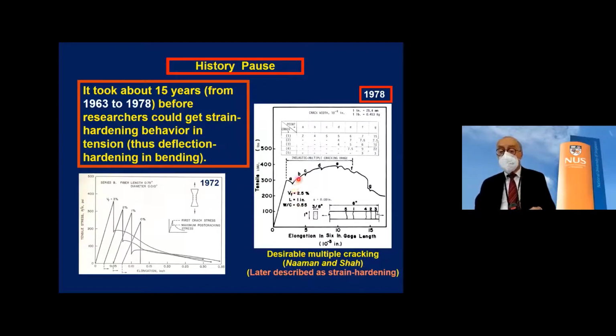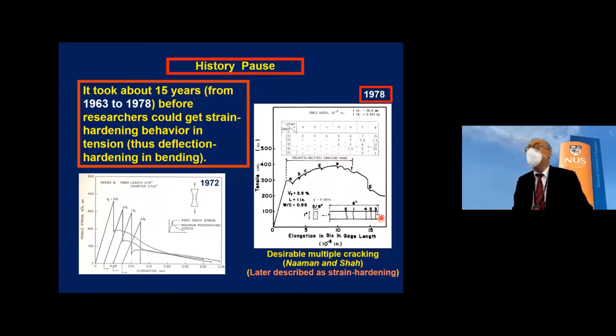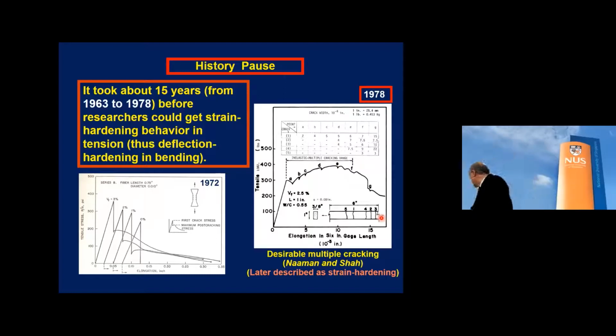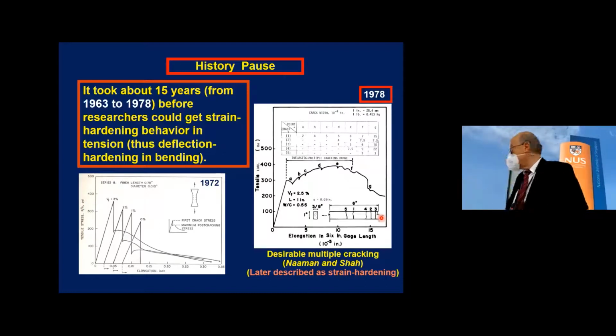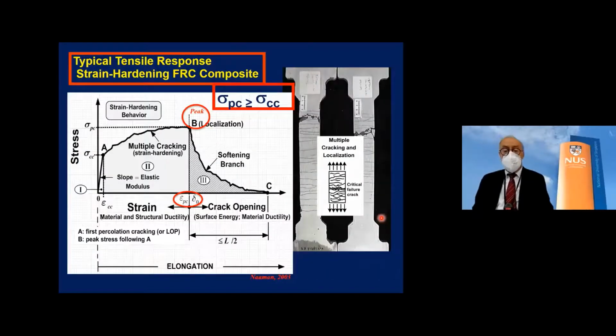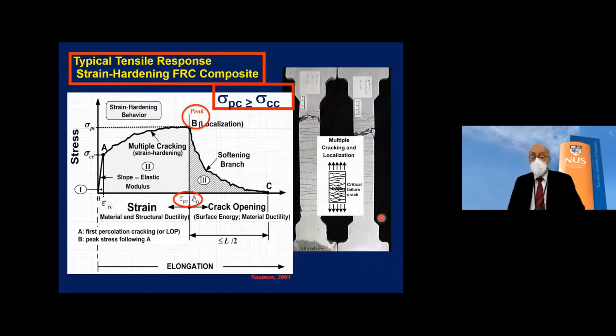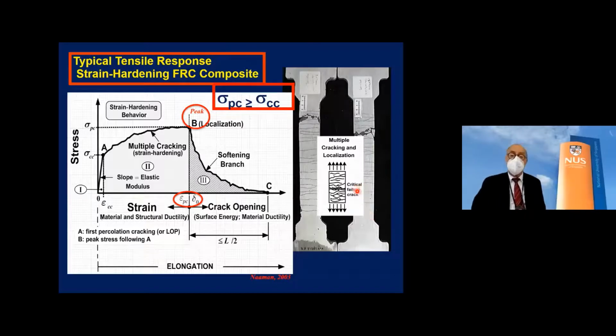And we observed several cracks. We observed this load maximum after cracking larger than the load at cracking. We even were so interested that we measured somehow the width of each crack and the order in which they came. At the time, we looked at this. I said, this is great. We called it desirable multiple cracking behavior. We didn't call it strain hardening, as later on we will. But we tried something. In fact, later on, today, using all our knowledge, we call this behavior a strain hardening behavior.